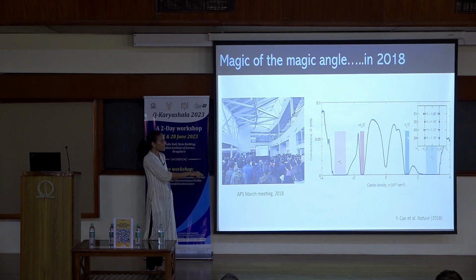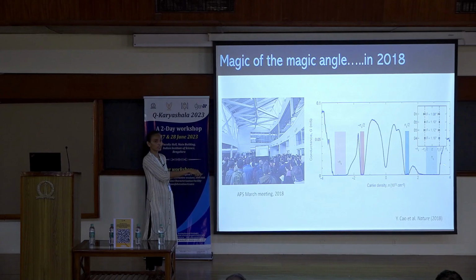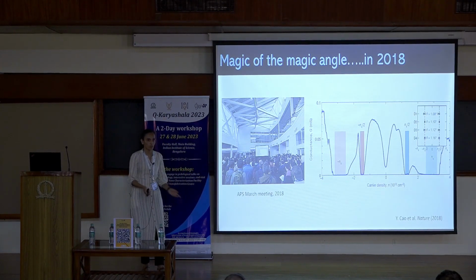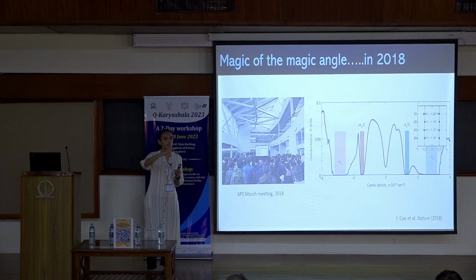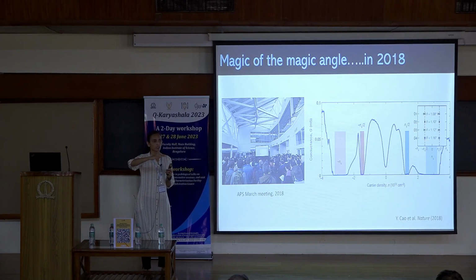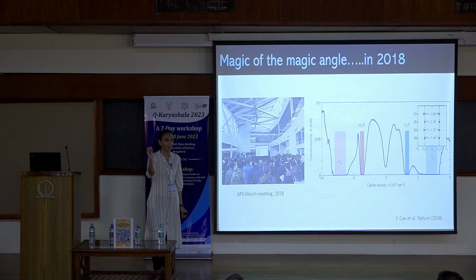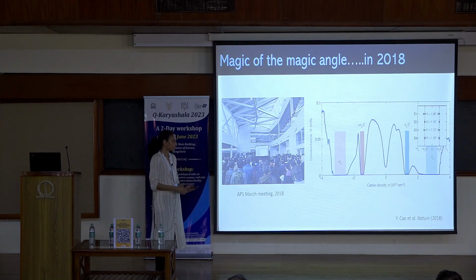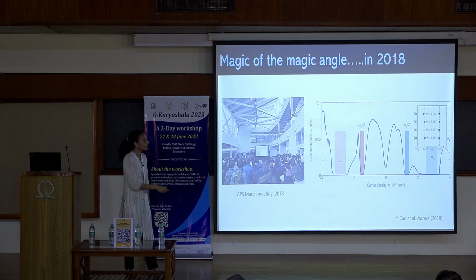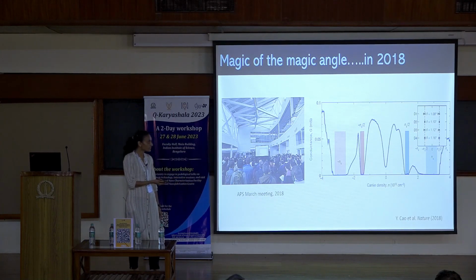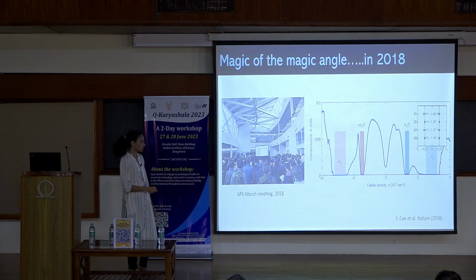Now what you see here is there are these additional dips when half of the valence band is filled or the conduction band is filled, and when that valence or conduction band is fully filled. So there are two things here. You can access the band fully, and there are these additional insulating states that appear. So what we're talking about is you have electrons in a band and you fill the band only up to half of the band. For people who are familiar with it, if you have a half filled band, it's normally a metal because you have an additional state just beside it, which can take the electrons. In this case, they found that they have insulating states, and these insulating states are signatures of emergent phases, which you were asking about.